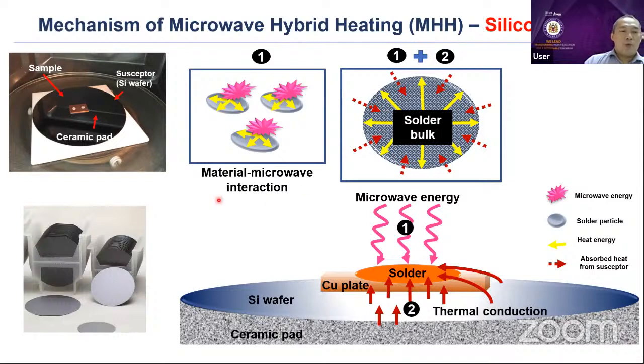So when we do the heatings by the microwave heating hybrids, it's starting by supply the microwave to the sample, and this one is the spark produced from the sample because we are dealing with the metals, right? And then the yellow one here is the heat energy. They will disperse, okay, disseminated on the materials. But as I said before, this one is not enough to make the samples. That's why we need to put the silicon wafer at the bottom of the sample.